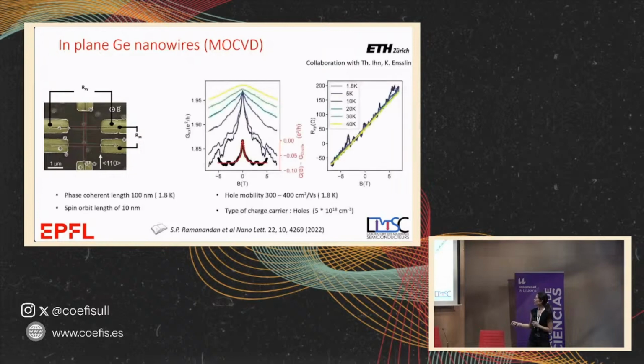So we did this, and we measured the mobility. We have about 400 centimeters squared per volt second, which is not very high in general, but that is very high for a nanowire. And we identified that we have holes, positive charges, and that's the one that we want to have for the spin qubits. It has to be holes.